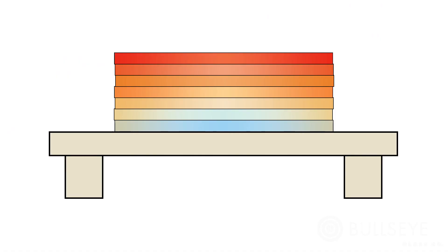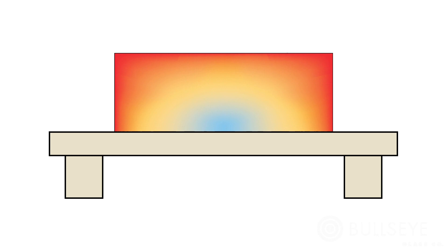This is because the individual layers can expand and move independently without building the kind of stress that leads to thermal shock. The solid block must be heated more conservatively to avoid temperature differences that can cause thermal shock.